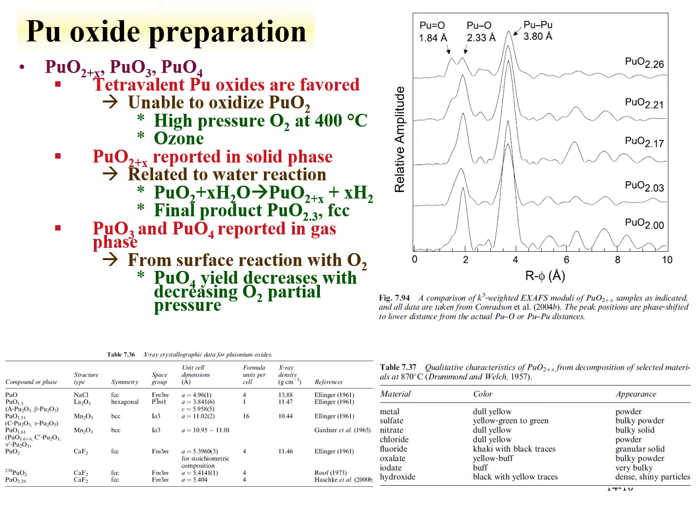This has been related to some water reactions as shown here. Also shown here is some XAFS data, where as we go from PuO2.00 to PuO2.26, what's observed is the growth of this plutonium-oxygen double bond at this peak. This is indicative of the formation of oxidized plutonium species.